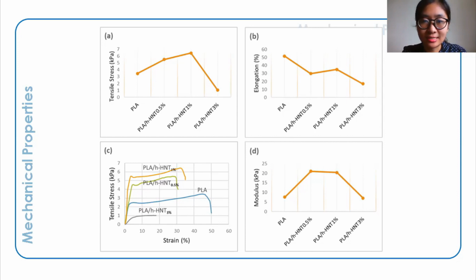The hydroxylated HNTs may not have been enough to be completely dispersed into the polymer matrix, resulting in increased rigidity of the composite fiber mass and poor mechanical property, as seen at 3% HHNT content.